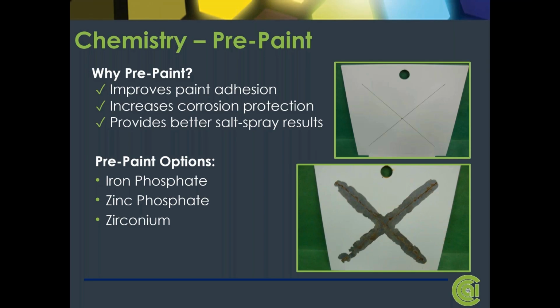Now, with pre-paint, there are several options. You've still got your iron phosphates, which are very predominant in the industry. Many people are still using those. They're workhorses. They're fairly durable. Some of the drawbacks: they do create a substantial amount of sludge in solution. They require heat to run, typically around 140 degrees Fahrenheit, plus or minus 10 degrees Fahrenheit, and you're going to get somewhere in the neighborhood of 30 to 70 milligrams per square inch coating weight when you use an iron phosphate.